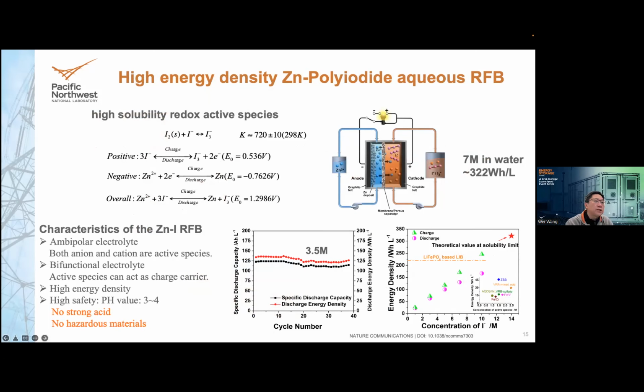Another example of the design of the contact ion pair is the zinc polyiodide. So I came from a lithium-ion battery PhD study, so my goal was always to increase the energy density, same as in the redox flow battery research. So what we found is this iodide chemistry. Iodine barely dissolves in water. It's a solid, but when it is present with excess iodide, it will actually form a triiodide. The triiodide has a huge solubility. I think it's around 7 molar in the water, so that translates into a very high energy density.